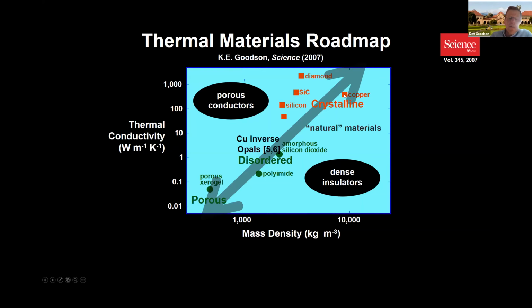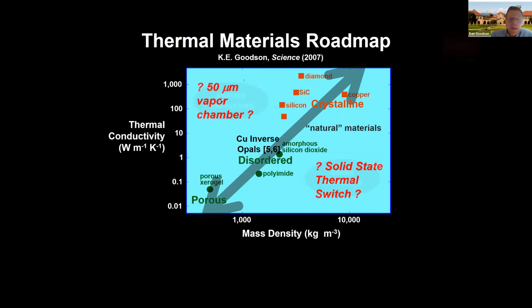If you try to make a super dense thermal insulator, well, that's hard, but it can have a big impact. Or if you make a porous heat conductor that actually has a low density, that could be very important. And so one of the things I was thinking about is that the areas of impact would be in those realms. And in fact, there's work that we're doing in my group on trying to develop a solid-state thermal switch to route heat that takes advantage of low thermal conductivity at high density. And we're also working, for the ASCENT and the POETS Center, on making super small vapor chambers that take advantage of high conductivity in porous media.